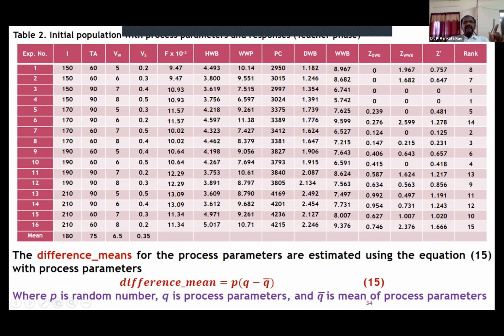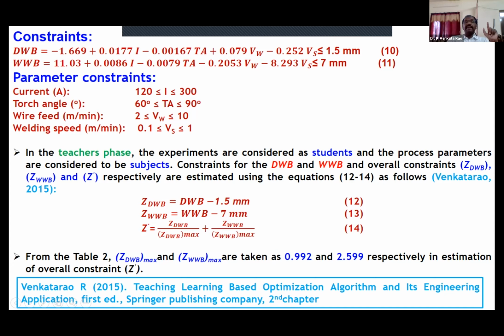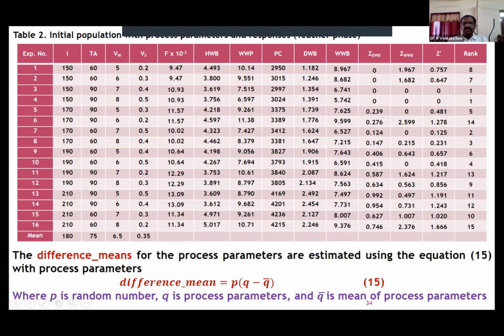Now the constraint for depth of weld bead: the value is 1.182, so 1.182 minus 1.5. Where we get a negative value, negative values are taken as 0. Positive values are taken as they are. For experiment 4, 1.391 minus 1.5 gives a negative value, so we have taken 0. For 1.739 minus 1.5, we get 0.239. Like that we have taken all the negative values as 0, and positive values as they are.